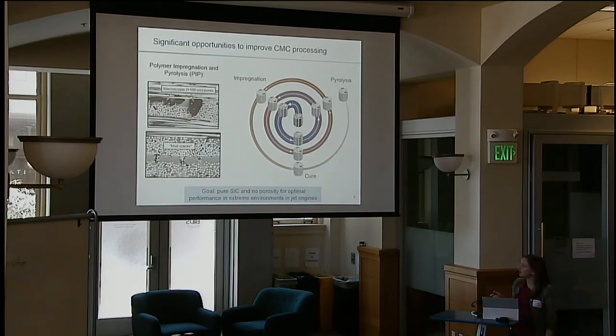In this technique, we start off with a fiber bed. From the transverse view, these look like circles. We flow a pre-ceramic polymer through this fiber bed, and we can then cure and pyrolyze this polymer to convert it to silicon carbide. During the pyrolysis process, the polymer shrinks, and then we end up with a microcrack structure. So over this entire process of impregnation, curing, and pyrolysis, we can form big bubbles and cracks during pyrolysis, and this leads to a very porous matrix. So we then repeat this cycle multiple times, re-infiltrating the polymer into this crack network to further build up this matrix.